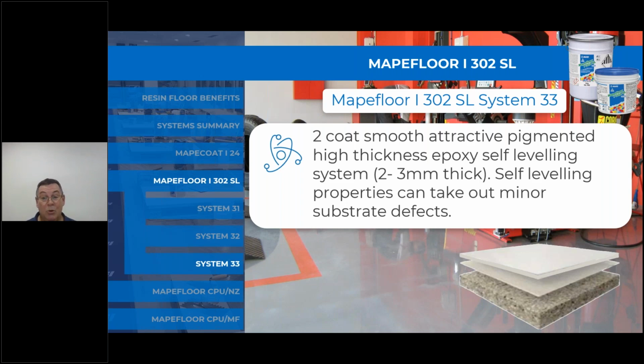So a 2-coat, smooth, attractive, pigmented, high-thickness epoxy self-leveling system, generally 2 to 3 millimetre thick. It's a self-leveling material, and it can take any minor substrate defects out also. But defects should be attended to before the floor goes down to ensure that the smoothest of floors can be finished.